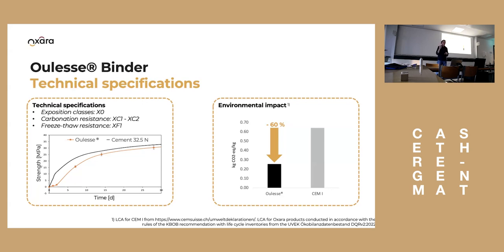Exactly. And then the environmental impact: if you compare it to CEM I, the Oulesse saves up to 60% of the CO2 footprint. So to summarize, for this new binder, as is often the case with alternative binders, you need to be careful with the exposures you use it in, because it cannot fulfill the carbonation limits. And in this case, we have the limited early age strength development.